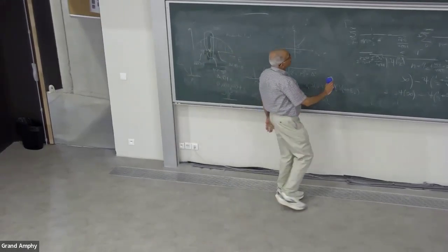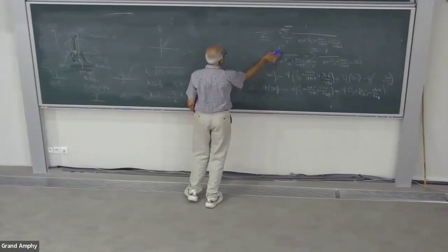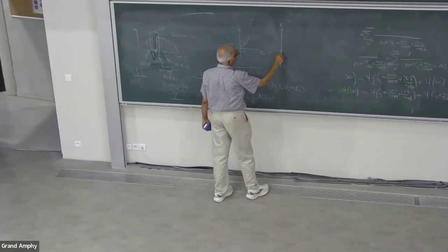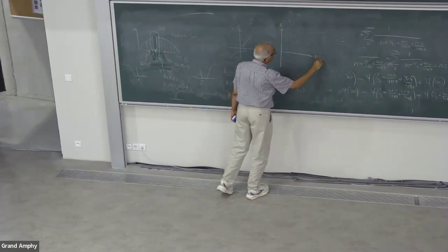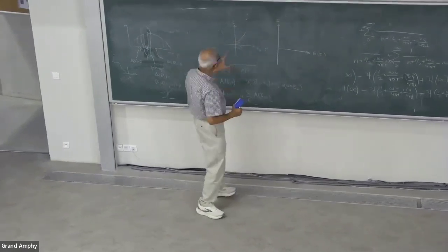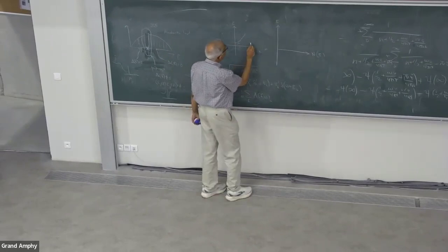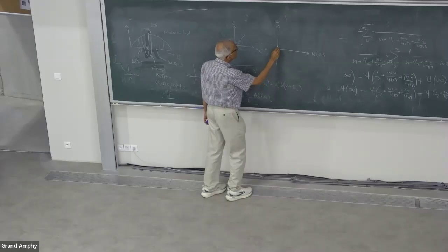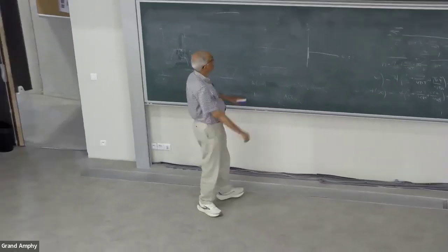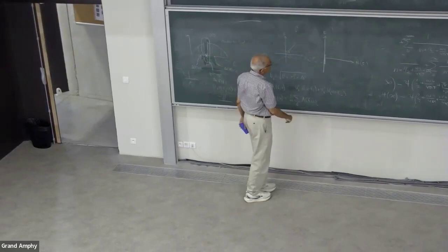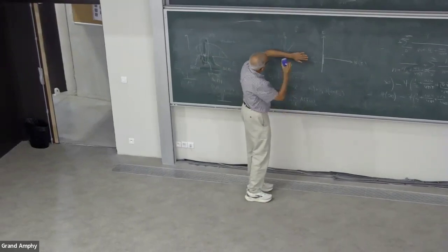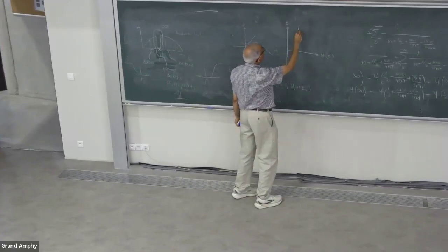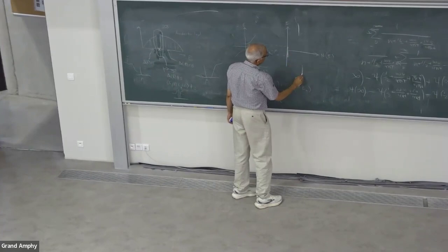Now everyone is with me as to what I've drawn? Okay, so if you calculate the density of states, let me draw it this way. Since I have energy going up, let me draw n of E sideways. Of course there are no states in the gap, so the density of states at zero temperature is 0. If I go very far to positive and negative energies, you don't see the gap. You just see the original band structure, which is just some constant density of states.